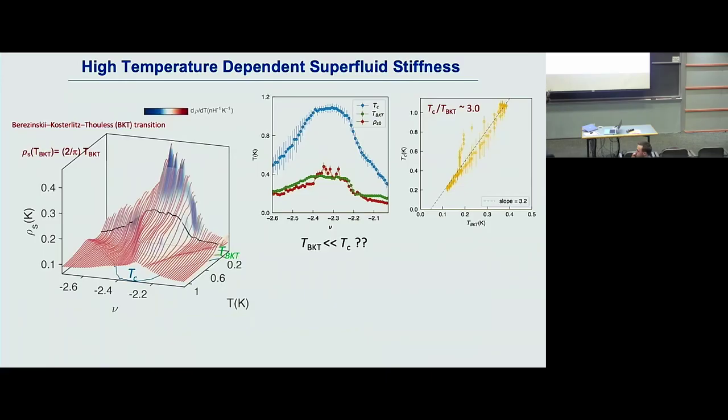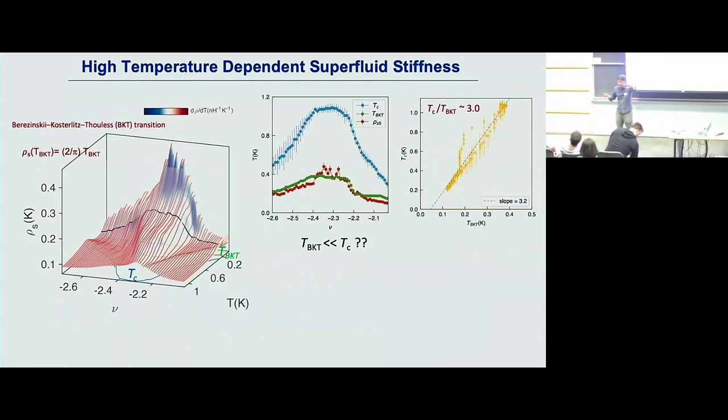TC is basically transport measurement: at the foot of the transport rise, if you measure the IV characteristic, you identify it as a BKT transition temperature from the transport. So this TC is basically this BKT from transport. You can just put it this way: it rises from 0. That has been measured many times.